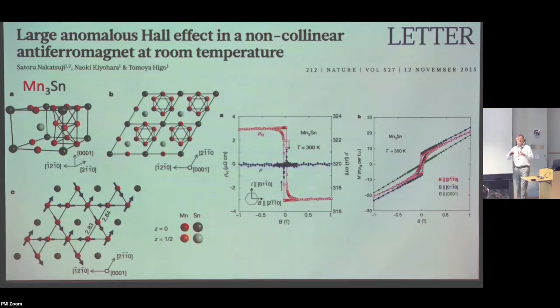Now, the Kagome lattice we've been interested in for many years because of its frustrated magnetism. But that's when it exists as a two-dimensional structure. In this case, it's actually a layered structure, and there are very strong interactions between the layers. This is a metallic system, and so it has, I would say, nothing to do with the spin liquid physics that people have wanted to see in the Kagome lattice. But it does have to do with the triangular nature of the structure, as well as the low coordination number. We could say that they play a role.